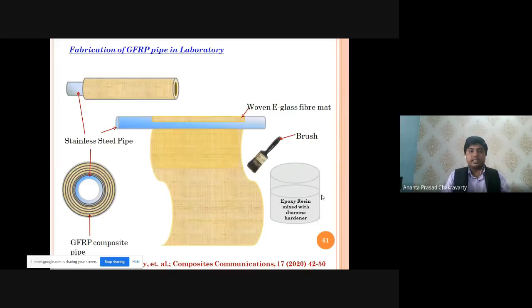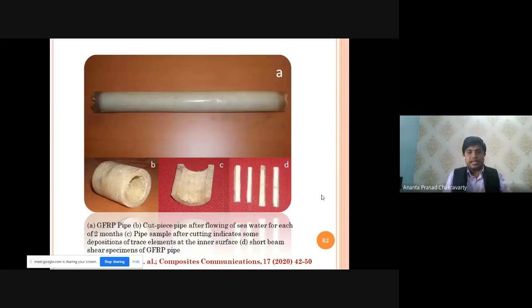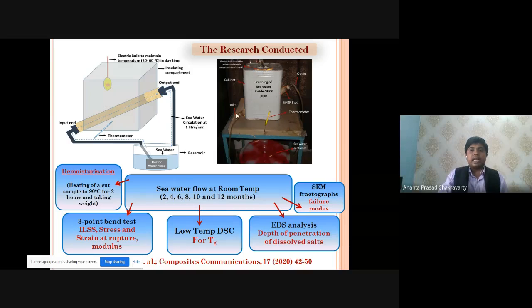It can flow inside it. Hence I have fabricated a glass fiber reinforced epoxy pipe by this method. I have taken a stainless steel pipe, then wound the glass fibers over it, then applied the polymers, then hardened it. After that, as you can see in the diagram, this tube is arranged in this experimental arrangement to run seawater in the lab for 1 year continuously, and I have inserted an electric bulb